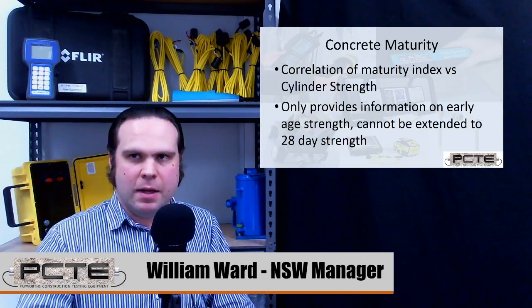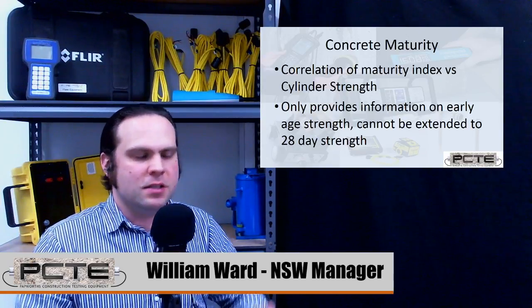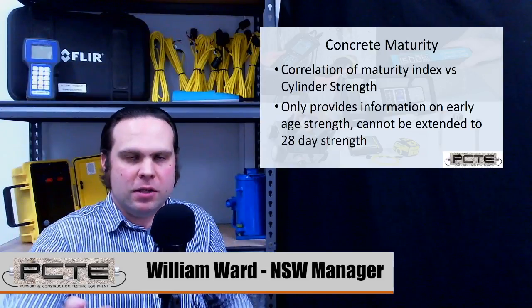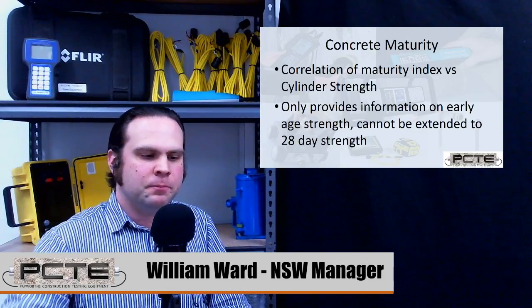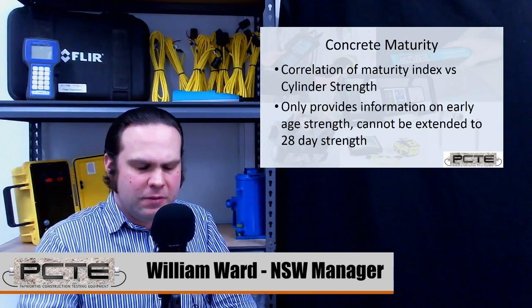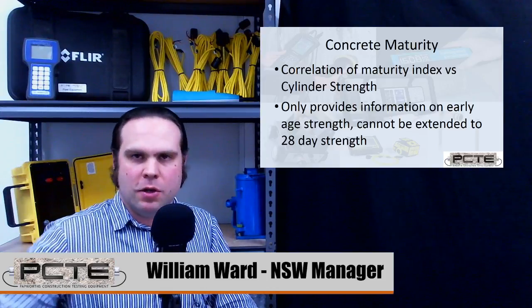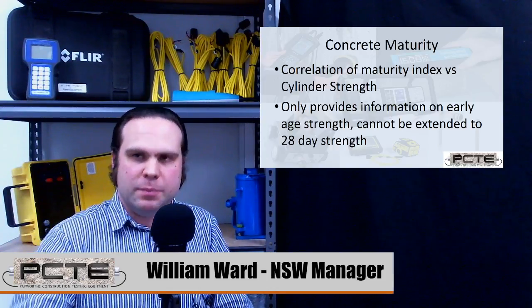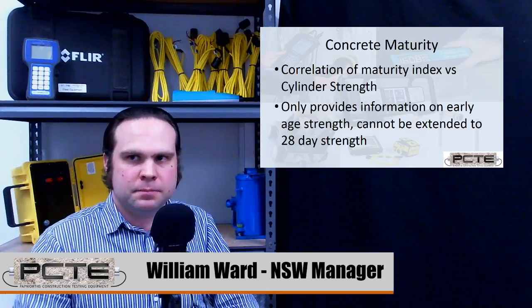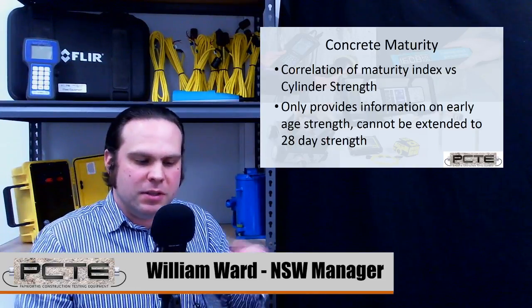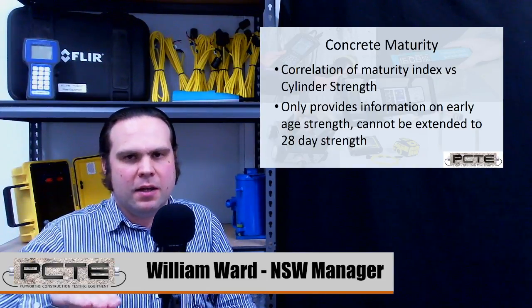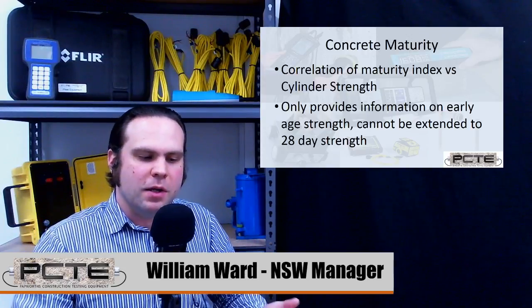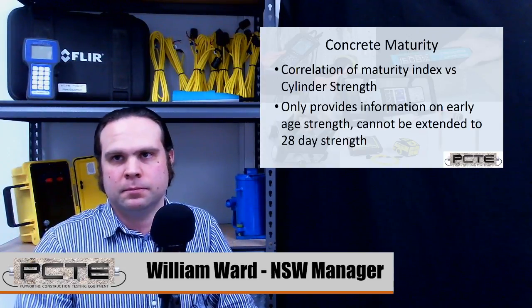If you take a maturity reading system and you check a value after 20 days, 30 days, 40 days, there will be a continuing increase in strength of that sample. But even if the curve has been set up out to those higher strengths, the relationship is better earlier on in the curve. And there may be some other applications using similar techniques, but maturity as it's commonly used is an early age strength only tool.